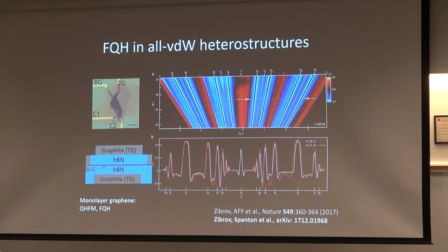So it's 4 or 5 electron volt energy gaps. It's atomically flat. You can get large single crystals, and you can make structures that have graphene sitting on hexagonal boron nitride. And that had a major improvement in the quality of both zero field transport properties as well as high magnetic field properties. Whether you can see fractional quantum Hall states, for example, whether you can see that in fact the degeneracy lifting within a Landau level is arising from interactions rather than from disorder.